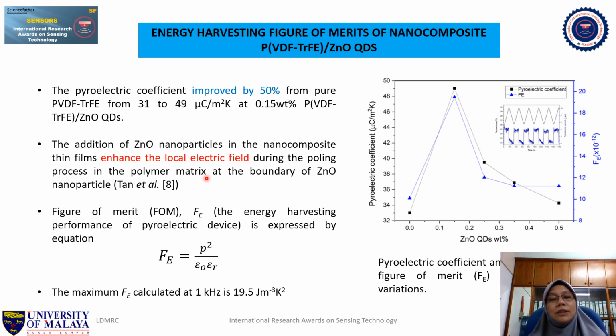So according to Tan et al., the addition of zinc oxide nanoparticles in the nanocomposite thin films enhanced the local electric field during poling in a polymer matrix at the boundary of the zinc oxide nanoparticle. So the highest or maximum figure of merit obtained from this nanocomposite at 1 kHz is 19.5 joule per meter cube Kelvin square.